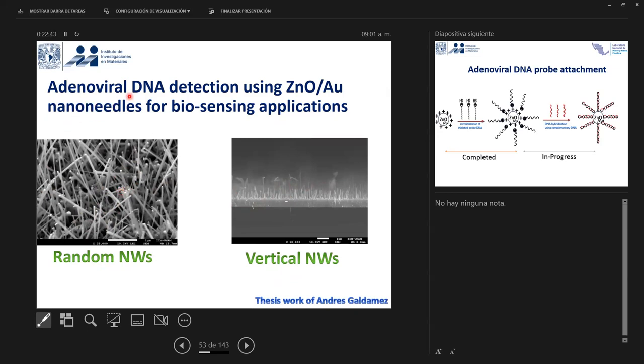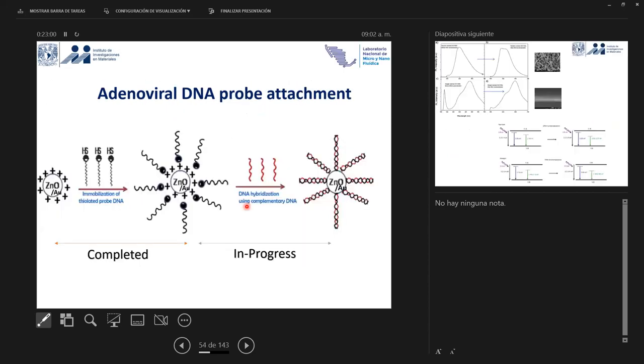First, we wanted to check if there is an interaction or not, because these nanowires are inorganic and then we have organic DNA. How will the interaction happen? And if there is some kind of interaction, which of these orientations is better for these optical biosensors? So this was the growth part. Now the characterization part. In this case, we have zinc oxide gold nanowires. We did the immobilization of thiolated probe DNA, that's only one strand. And then we found this interaction with different kinds of characterization techniques. I'll be showing the results in a minute or two. And this part is completed.